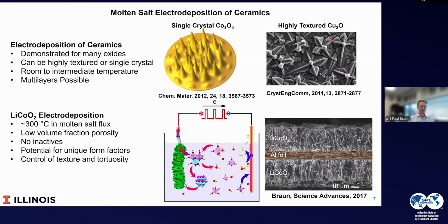And so now in the electrodeposition, what we do is we take a dissolved metal and convert that to solid ceramic, in this case, lithium cobalt oxide. And by converting it to lithium cobalt oxide, electrochemically, we can control the tortuosity and we can control the crystal texture. And so the potential now is here for a system that contains no binder and no conductive additive, is directly growing on the current collector, and is growing with a very high degree of orientation.